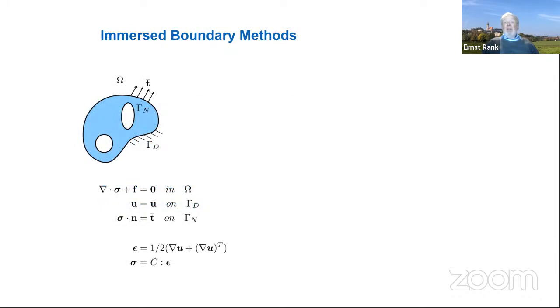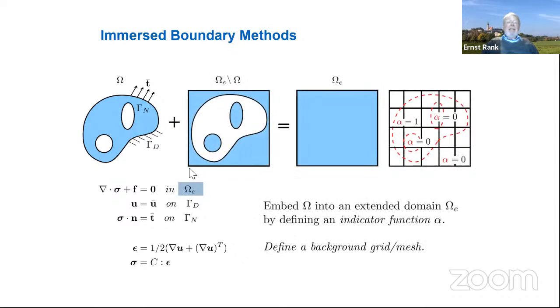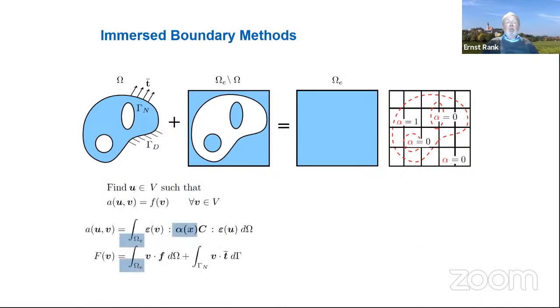Well, we are using immersed boundary methods to simulate this composed structure, and these immersed boundary methods, I've talked about this very frequently. I give only the general idea. So we embed a structure, and this may be complex, into a larger one, get a simple geometry which is meshed in a simple grid. And in addition to this, we have an indicator function which tells us what is inside and what is outside the domain of computation. So this translates to a formulation on this extended or immersed domain with this indicator function.